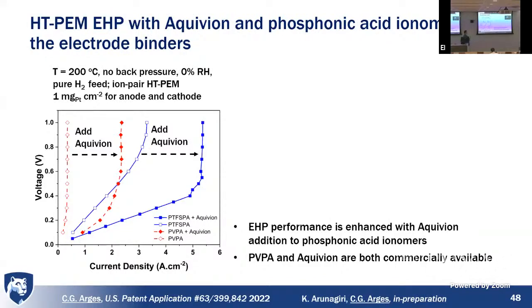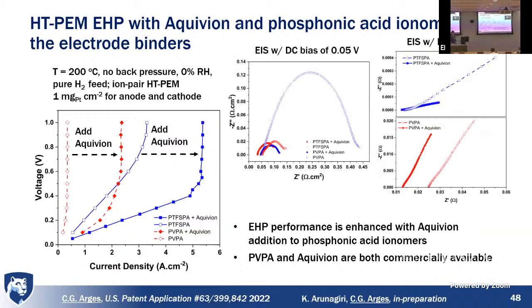We see, okay, yeah, we can pull a lot more current. We can then get to some current. This here is our phosphonated ionomer by itself, but then when we add Aquivion, we could go up to 5 amps per centimeter squared. That was exciting. So this performance was enhanced with Aquivion in the cell. But what I want to tell you is how they impact reaction kinetics and gas transport.